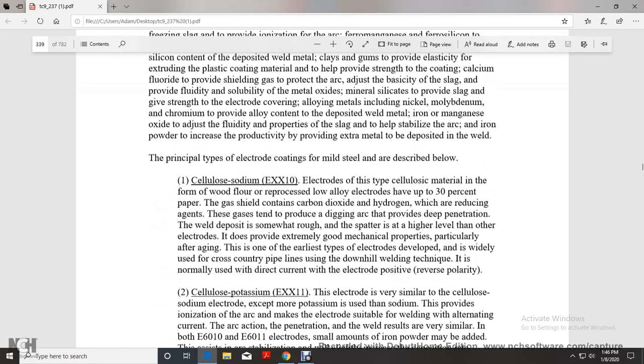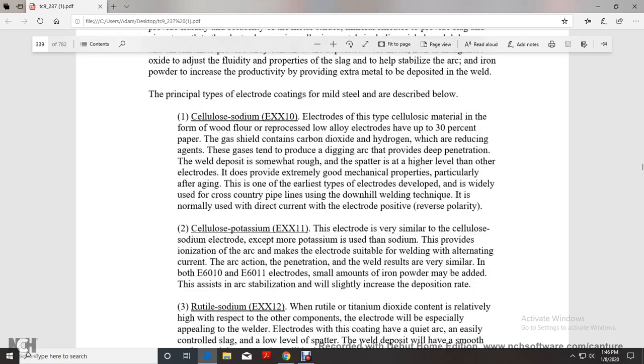The principal types of electrode coating for mild steel are described below. Cellulose sodium, the E6010 electrode: the cellulose material is in the form of wood flour, and reprocessed low alloy electrodes add up to 30% paper. The gaseous shield contains carbon dioxide and hydrogen, a reducing agent, which produces a digging arc and a deep penetration weld deposit, somewhat rough, with higher spatter levels than other electrodes. It does provide extremely good mechanical properties, particularly after aging. This is one of the earliest types of electrodes developed, widely used for cross-country pipelines using the downhill welding technique. It is normally used with direct current electrode positive, reverse polarity.